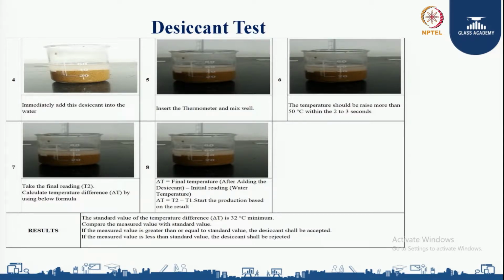Start the production based on the result. The standard value for the temperature difference is 32 degrees centigrade minimum. Compare the measured value with the standard value. For example, if my room temperature is 25 degrees centigrade and my desiccant temperature comes to 75, then 75 minus 25 gives delta T of 50 degrees centigrade, and the minimum required is 32 degrees centigrade. If the measured value is greater than or equal to the standard value, the desiccants shall be accepted and are in a position to absorb moisture. When the measured value is less than the standard value, the desiccant shall be rejected.